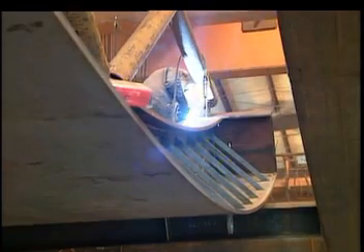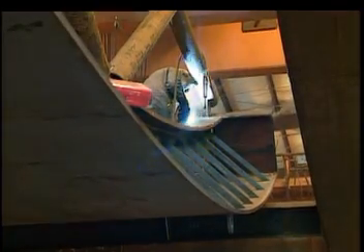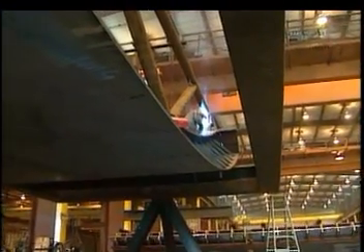Because the weld puddle is large and fluid, the process can only be used for flat or horizontal welding. Due to higher heat inputs, spray arc can cause undercutting. The spray arc process has a very controlled, stable arc with little spatter and minimal shorting. Molten metal streams from the electrode end. The magnetic field from the arc surrounds the wire, and the high magnetic force pinches the wire down at the end. Molten droplets stream through the arc to the workpiece.